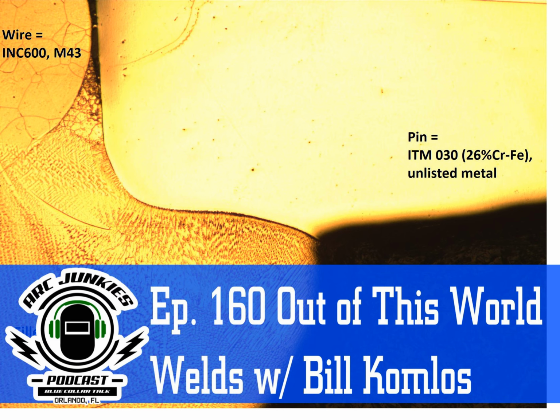Okay, Magic Tony will say, well, you can weld for die penetrant or you can weld for strength, because we do a lot of fuel cylinders. They make propellant for these missiles and stuff. And so if stuff gets caught in a pinhole or something like that, it could blow up the whole system. That's why they build the roofs to blow up instead of the walls, so that it blows up and out and doesn't blow out into the communities. So you can't have pinholes in aluminum.